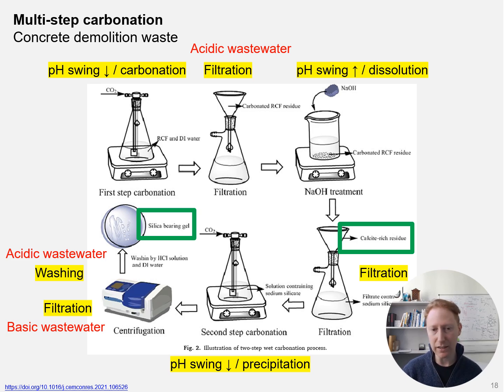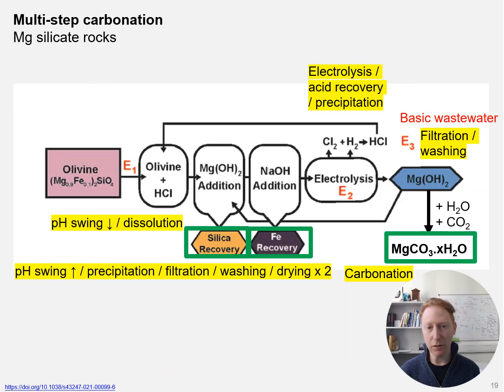The carbonated calcium material is removed as a product, and it is typically a relatively pure calcite-based product, and the aqueous silica is precipitated through another pH swing step. That precipitated silica is then washed and is another product. So this means from multi-step carbonation processes, yes, the processes are more complex, but we can produce two or more products from them. The multi-step carbonation process is a little bit different for magnesium silicate rocks, and here is an